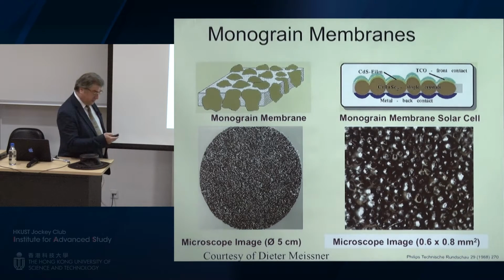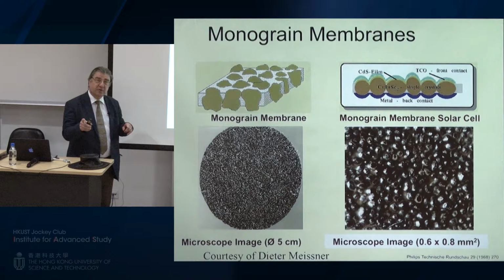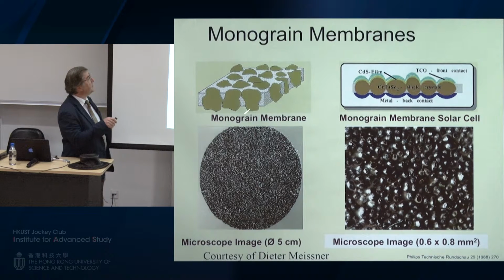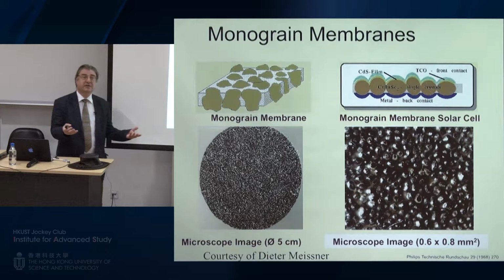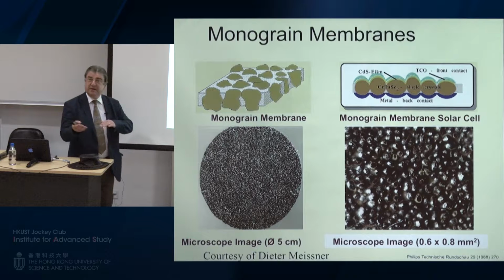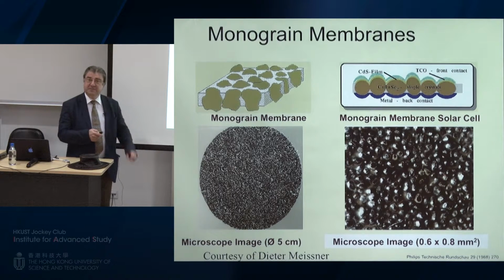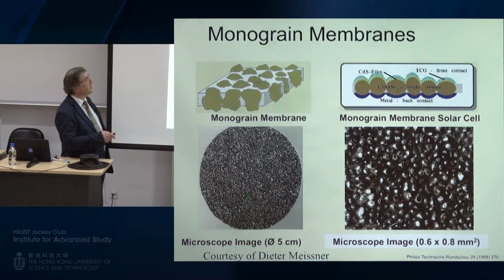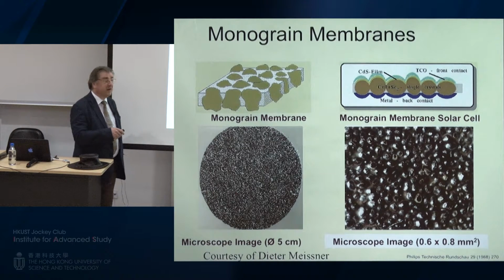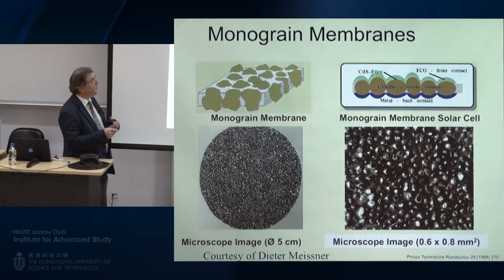And this is something which my good old friend Dieter Meissner was following, and he told me that this is actually a patent going back to 1968 from Philips. It's amazing that these people at that time made these kinds of solar cells, and these solar cells are based not on nanocrystals, but on microcrystals, grains embedded in a plastic matrix. If you polish this plastic foil on both sides, you can contact each of these microcrystals, which are single crystals, perfectly to make nice efficient solar cells. In those days, of course, people were using cadmium selenides, cadmium tellurides, all kinds of things. But we are now using more copper indium sulfide or copper zinc tin sulfide systems.